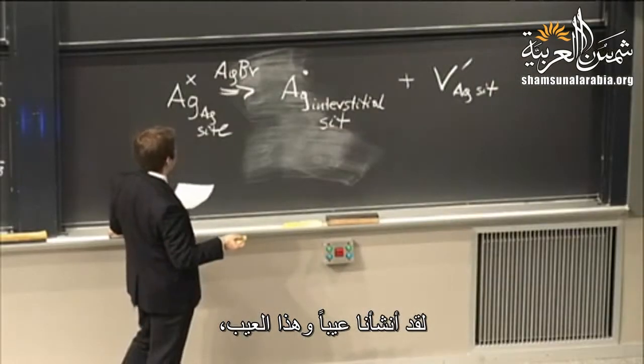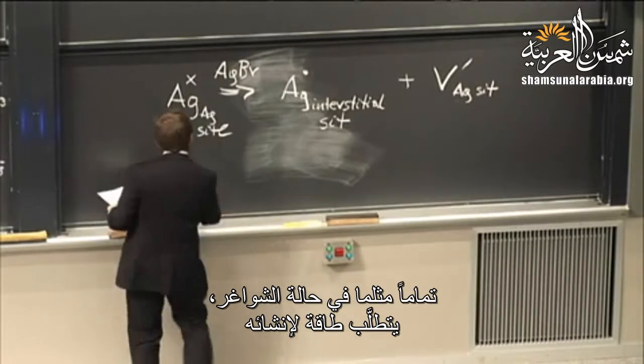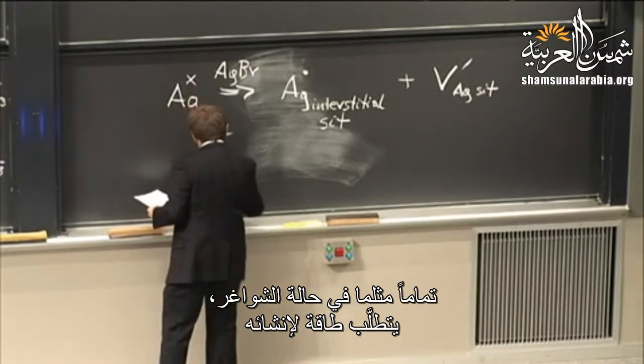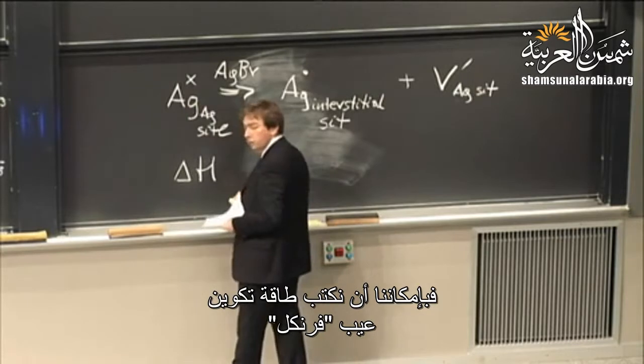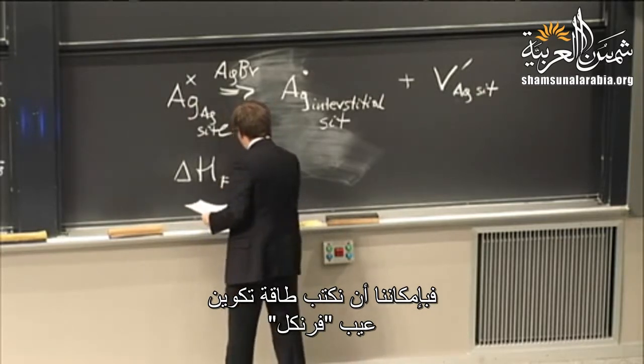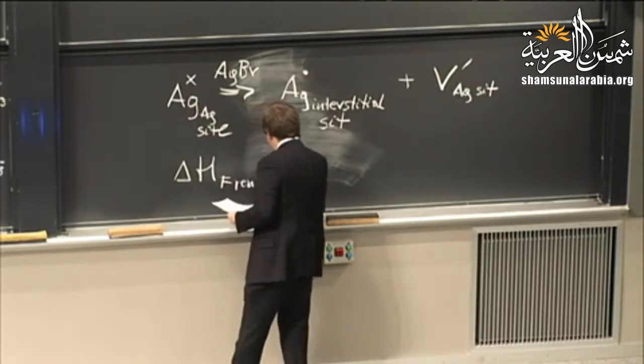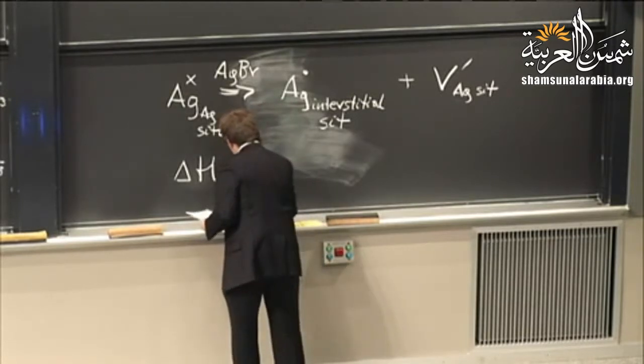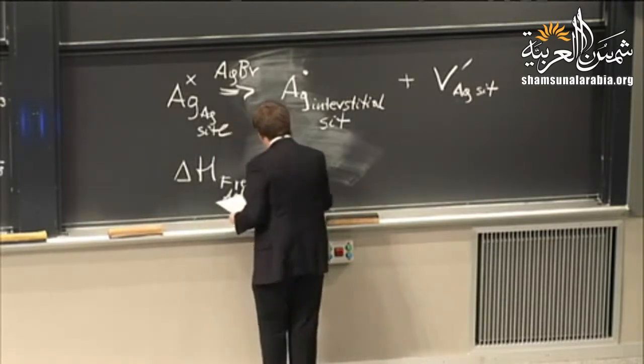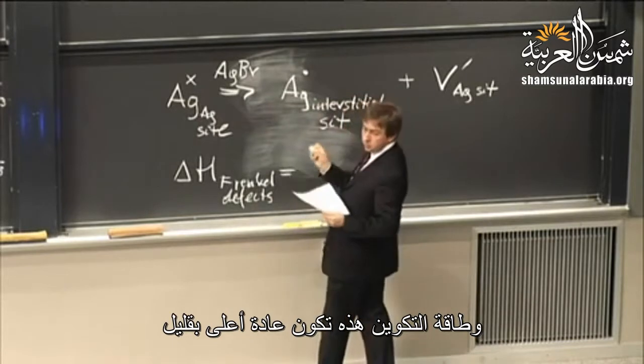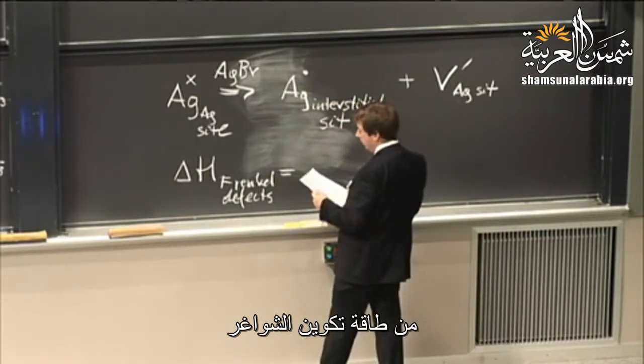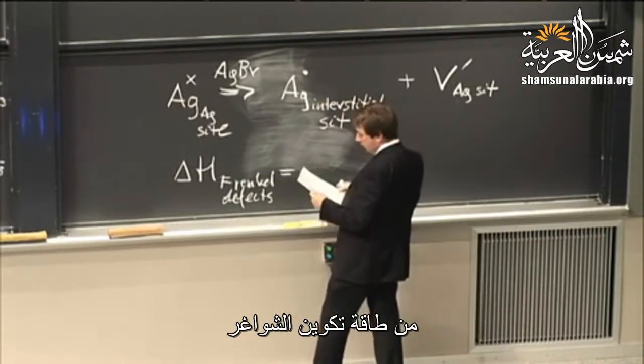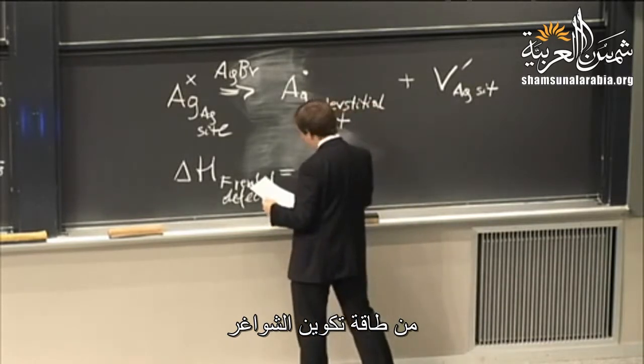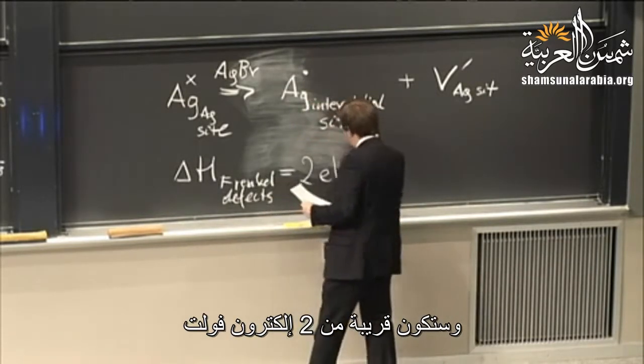And this defect, just like in the case of vacancies, costs us energy to make. So we can actually write down a formation energy for Frenkel defects. And this formation energy is usually a little bit higher than the formation energy of vacancies. So it's going to be something perhaps on the order of 2 eV.